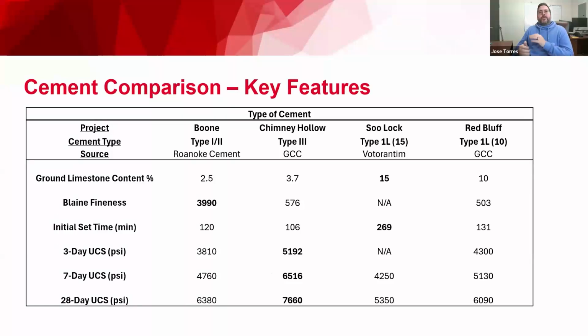These are just key features comparing all 4 of the mill certs we have for those cements that we used. You can tell the difference in the limestone content: 2.5, 3.7, 15, and 10. Some comparisons for Blaine fineness as well. There's a lot of interest in Blaine fineness and what that means in terms of grout travel and maybe a little bit of segregation, and how it interacts with pressure filtration is something we're going to be looking at in the future. I've heard it from multiple people in the industry now, so there's big interest there.